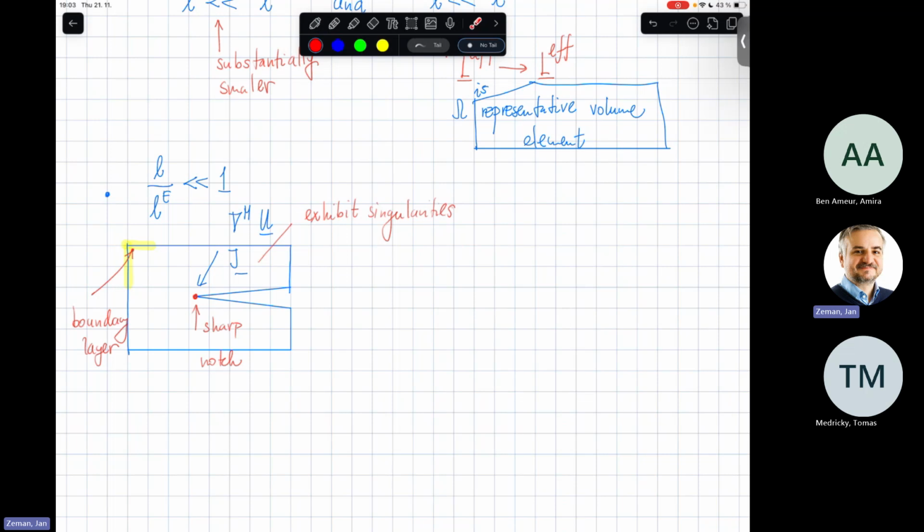So this is one thing to keep in mind. So for instance, if you would like to check the quality of your solution, you can rely on your homogenized coefficient somewhere in the interior, far from these possible features which make the solution, and again, particularly its gradients, vary very rapidly.